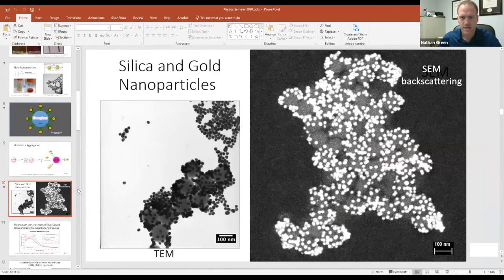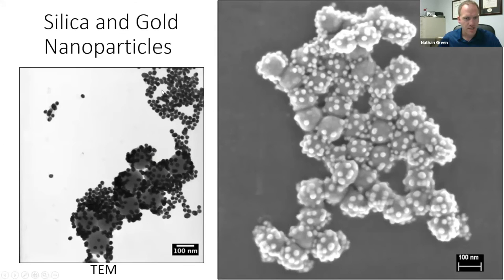So you can kind of see on this slide, sorry, I'm trying to manage my screen out of the way here. You can see that the particles here are not all stacked on top of each other. That's because these silica nanoparticles have a coating. And so it's important that you coat the outside with something at all times. If the coating goes away, then the gold starts to fuse together and they're no longer individual particles. They start to form bulk particles.